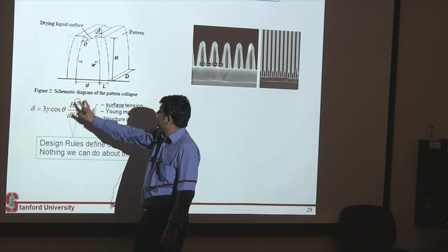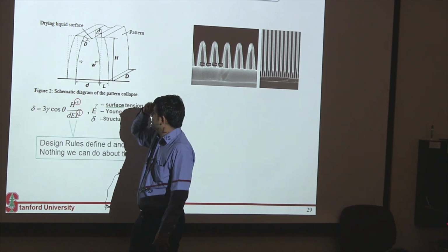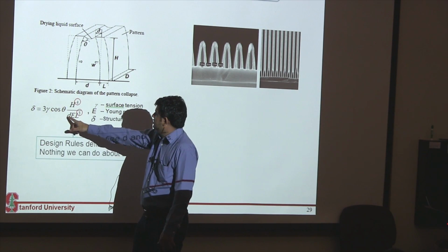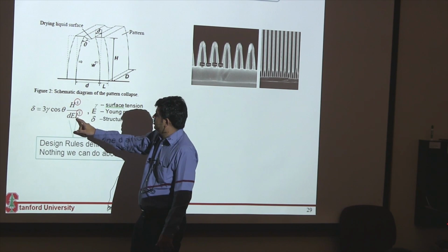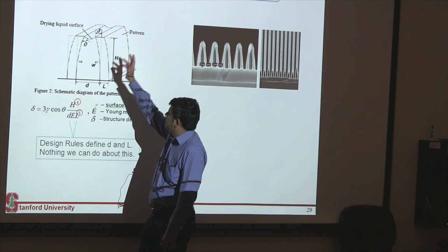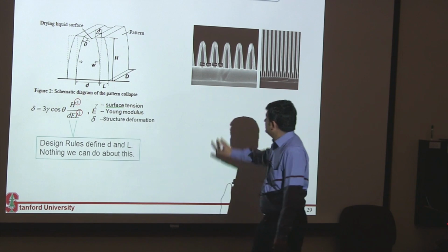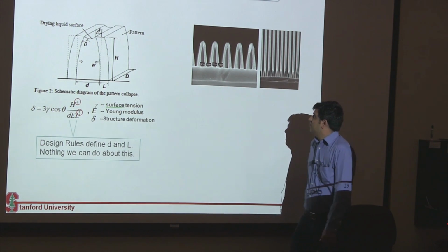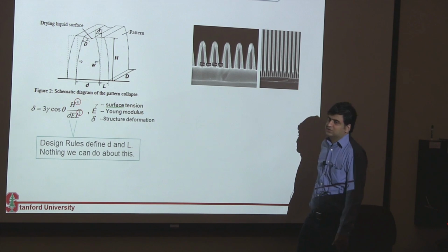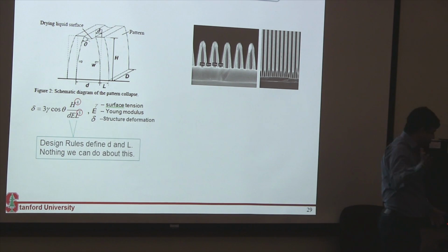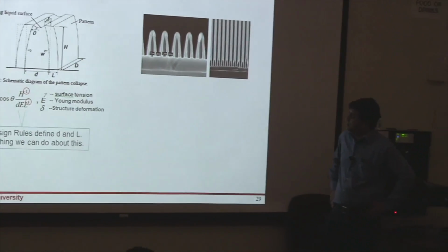If you space them closer, you increase it, but not as much, because one is inversely proportional to the 3rd power, the other one is inversely proportional to the 1st power. And when you make them taller, again, you make things worse. So if you make these tall and thin fins, they collapse, and this is showing some pictures of them collapsing with each other, or away from each other. So this is a big problem in making your fins taller and thinner, and also making them vertical.